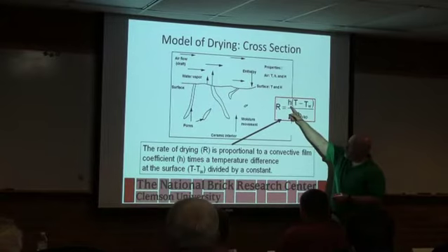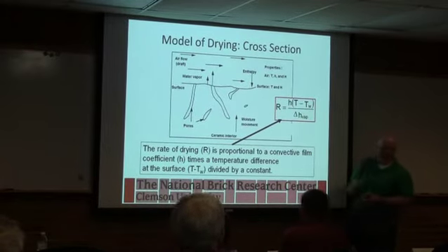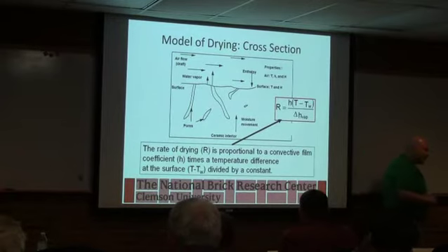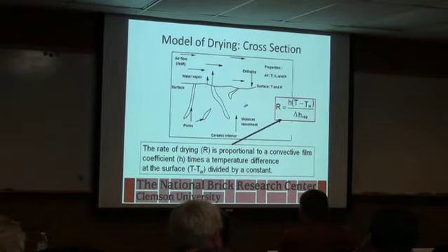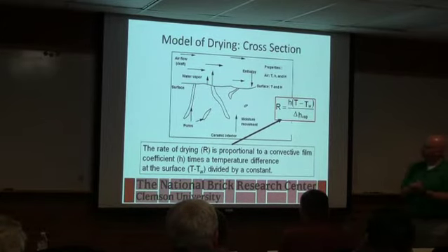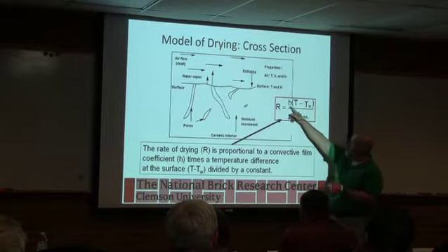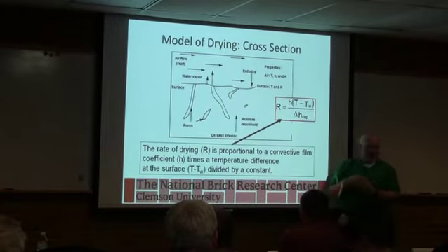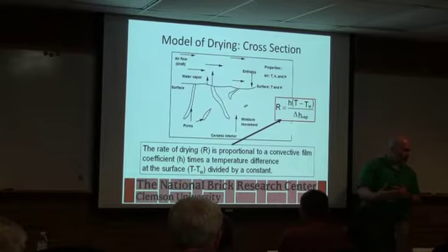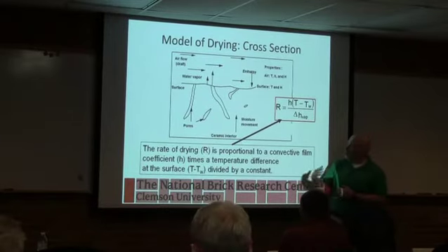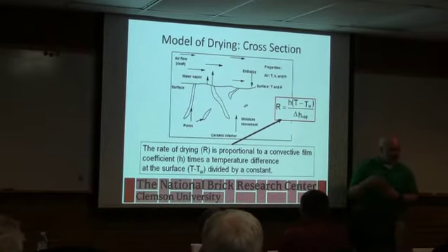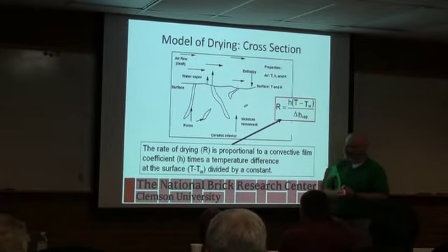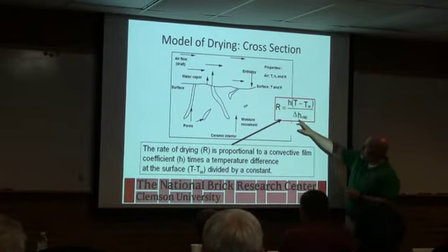This is a film coefficient, and a film coefficient has to do with how the air interacts with the surface. Do you have air blowing across the surface? How fast is the air moving? Is the air hitting the brick at 90 degrees, or is it parallel? Basically, it's a way of describing how well the air is exchanging its energy with the brick. So, are we doing a good job of heating up the brick with the air, or is there not much movement, not very efficient? And then this is the heat of evaporation.